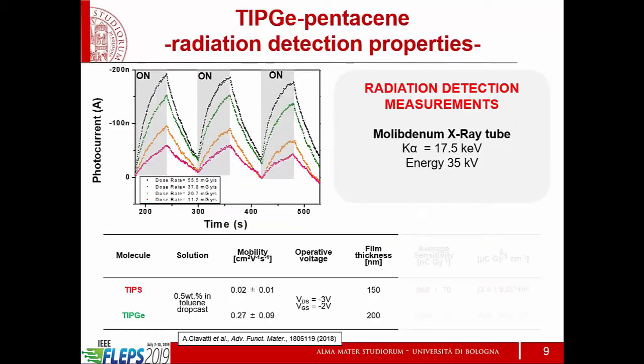What happened once we put and tested these new films as X-ray detectors? As you see, the on-off X-ray response goes on very nicely. And just another comment that I didn't make: it's really good because you see they're reproducible and the baseline does not drift, and that is the advantage of using the transistor structure. What is less good is the fact that you see they're very long in reaching saturation, and also the decay time is very long. And that is due to the photoconductive gain process, because being a trapping and detrapping process, it takes time. That is related to the trapping time of the charge.